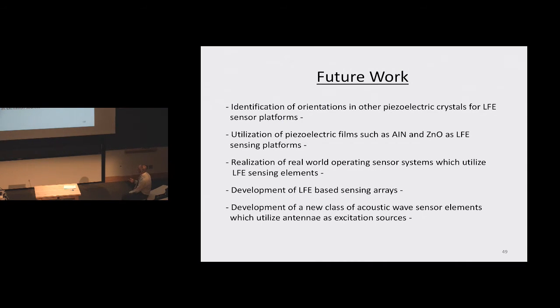What about the utilization of piezoelectric films, such as aluminum nitride and zinc oxide as this LFE sensing element? This thing can be made in the order of 1 or 2 microns thick, whereas the other ones are on the order of millimeters thick. Quite a difference. Very, very thin films means very high frequencies. Instead of talking about devices that operate in the 10 to 20 megahertz region, we're talking about devices that operate up into the gigahertz region.